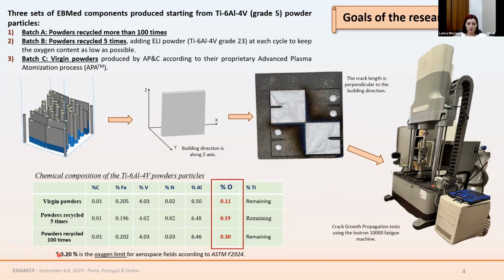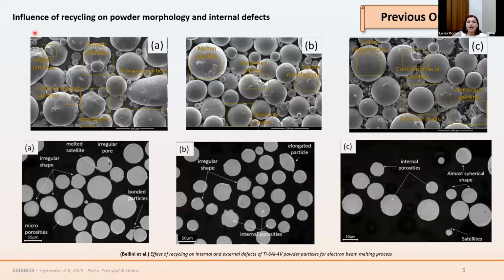Here below, I also wanted to highlight that the powder recycled more than 100 times, which is the batch A, exceeded the oxygen limit according to this ASTM standard for the aerospace field. So this is detrimental for these powders. And here there are some results from our previous work.